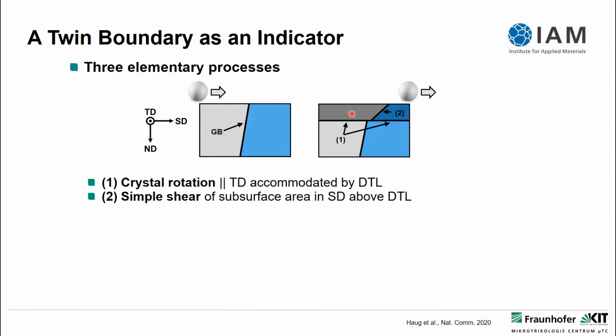Even though this is a dislocation mediated process, not a deck of cards, you can think about it like a deck of cards that you shear in the sliding direction. This is what we see because of the tilt of the twin boundary. Then we have the step, meaning highly localized shear happening at the lower dislocation trace line in sliding direction. We move this whole material above the trace line, this whole deck of cards as a whole, in the sliding direction.